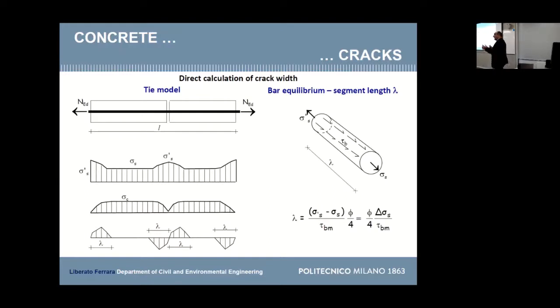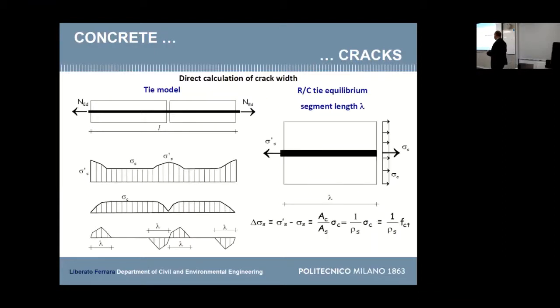Then you need some length, a transfer length or bond length, through which the stresses go from the steel to the concrete, are redistributed, so as to restore the coupling action between the two materials. And by simple equilibrium consideration, if you go back to any of your structural mechanics or structural design handbooks, you can find this equation. You find here that this transfer length is related to the bar diameter. Okay, keep in mind this concept.